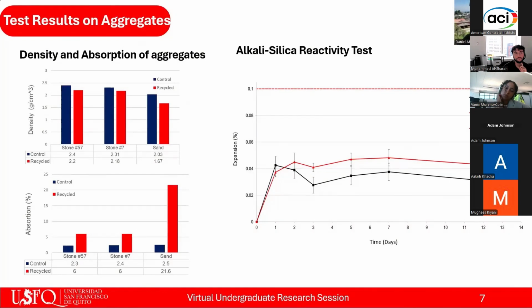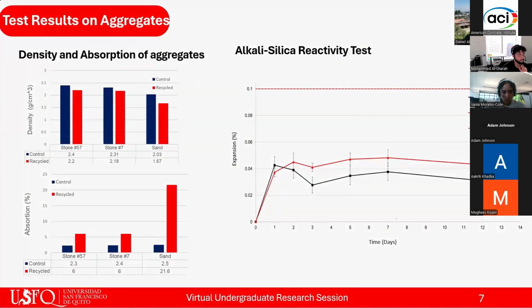To evaluate alkali-silica reactivity, 6 more bars, 1 by 1 by 11 inches, were prepared, 3 with recycled sand and 3 with natural sand, and submerged in sodium hydroxide at 176 degrees Fahrenheit for 14 days. Expansion was measured daily. Both sands showed similar trends, an initial expansion that quickly stabilized and remained well below the 0.1% critical limit defined by ASTM C1260. This suggests that neither sand presents a significant risk of internal expansion. These results are shown in a line graph with time on the x-axis and expansion on the y-axis.